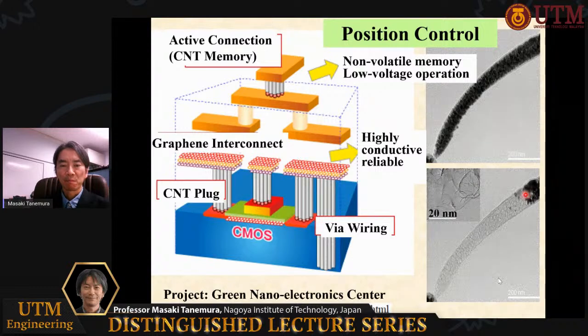The problem is the flake size. The flake size of graphene is still too small because the graphitization started from copper nanoparticles. So we tried formation of larger flake size of graphene.